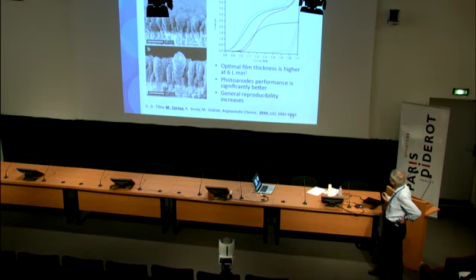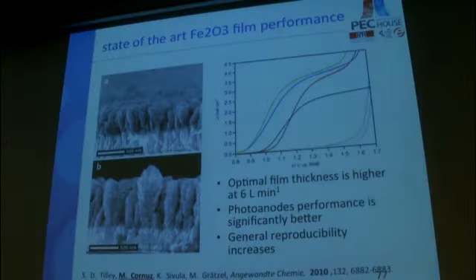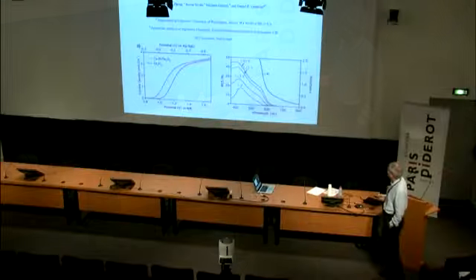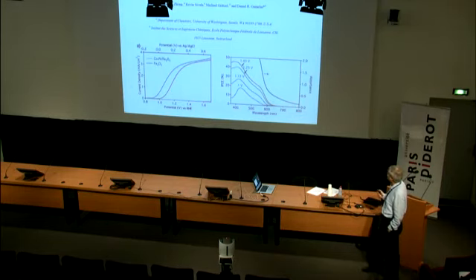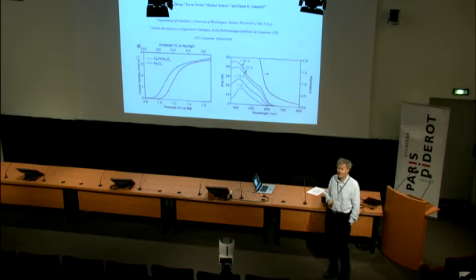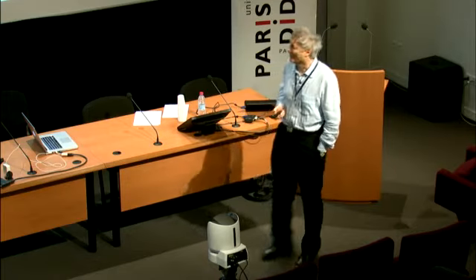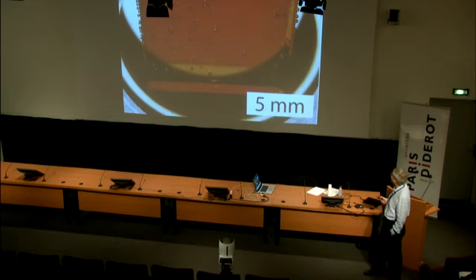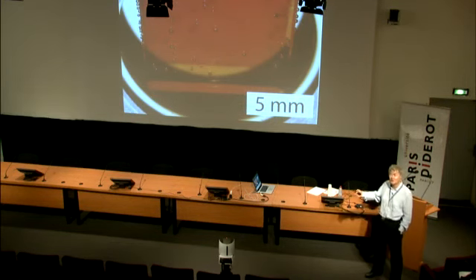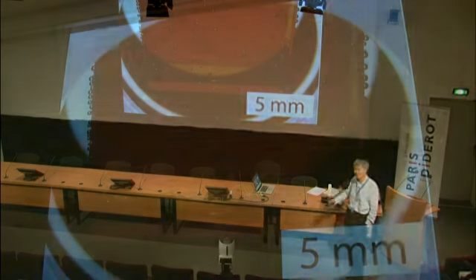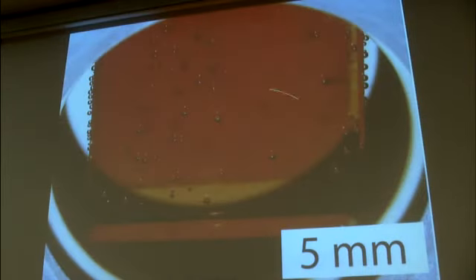And where we stand today, the latest is about 4 milliamps. That's in a tandem cell. If that's a supported current, it would be about 6% efficient overall solar to hydrogen. And so we also use the cobalt phosphate, which has very nice IPCE. So we're still working on those catalysts. Iridium oxide is certainly the best, but it's also expensive. So cobalt is a nice alternative. And we had proposed it even before Grätzel, and we used cobalt ions on the iron oxide surface in 2006 and published it in JACS.